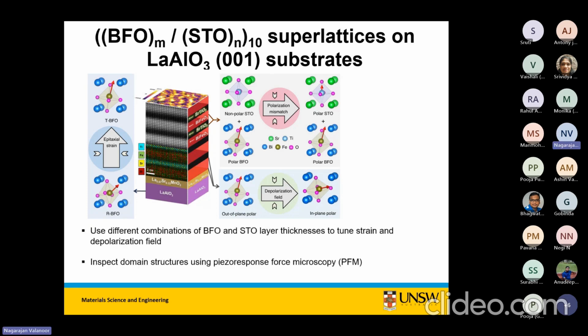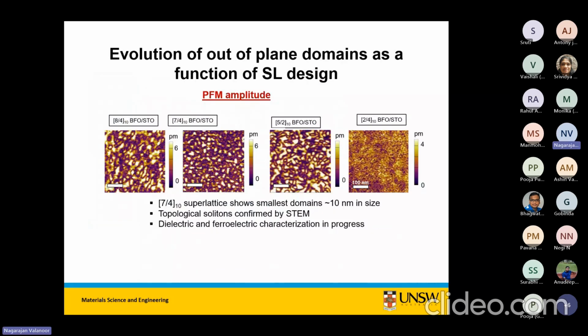So once you get these 2 combinations right, the next challenge is the design of the superlattice. For that, we did a whole lot of growths, and we find that there is this sweet spot. If you grow the bismuth ferrite layers too thick, then they will not form solitons and actually form beautiful labyrinth domains. I don't have that image here, but it's just spectacular labyrinth domains, which are in the Nature paper that Martin, all these guys published.